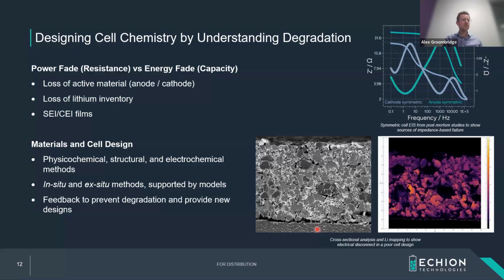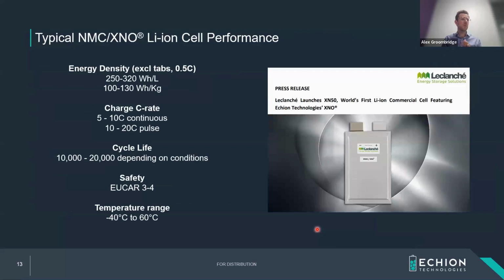So what about the cells themselves? How do they actually perform, and where are we in terms of commercialization? For a typical NMC XNO lithium-ion cell performance, you'd imagine specs roughly along the left as I show here. Energy density is similar to that of LFP graphite, hovering around the 300 watt-hour per liter range in terms of volumetric energy density and gravimetric, as you can see. And charge rates, depending on the trade-off you're looking for, either higher C rate or lower C rate, but always in that 5 to 10 C continuous and looking for higher pulses.